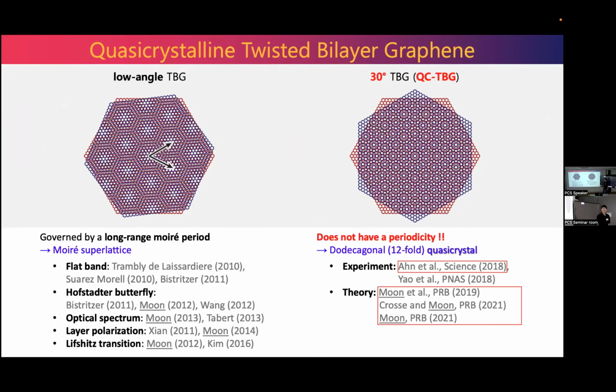But all of the research conducted so far has been done in low-angle twisted bilayer graphene, and there is a reason, because the period of a moiré pattern becomes longer as the rotation angle decreases. The period becomes 10 nanometers in 1 degree twisted bilayer graphene. But as soon as the angle deviates from the small angle, for example 10 degrees or 20 degrees, the moiré pattern period becomes comparable with the period of monolayer graphene. So it's usually not very interesting.